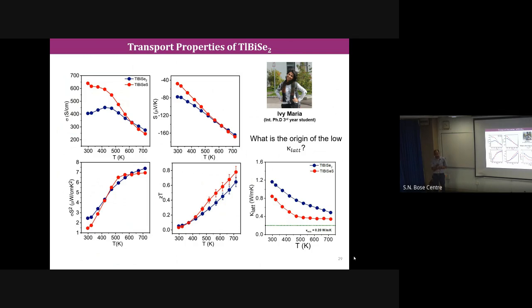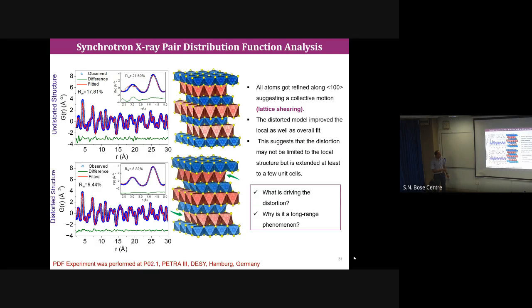But in this kind of compound, as some of you will know from the ferroelectric field, like bismuth manganite and all these compounds, the lone pair expresses itself very locally, okay, and that creates a local dipole. Exactly similar effect we see by PDF: the bismuth and thallium lone pairs express locally. But that should only explain the local distortion of the structure. But why is the global structure also distorted over a few units? Because this local perturbation created by the lone pair has been taken 2-3 unit cells away by this metavalent bond. Metavalent bonds are basically electron deficient bonds which are highly polarized, with short bonding. So if I have a local distortion, it propagates. That's why these compounds are highly soft, which is created by this lone pair distortion, mediated by metavalent bonding.